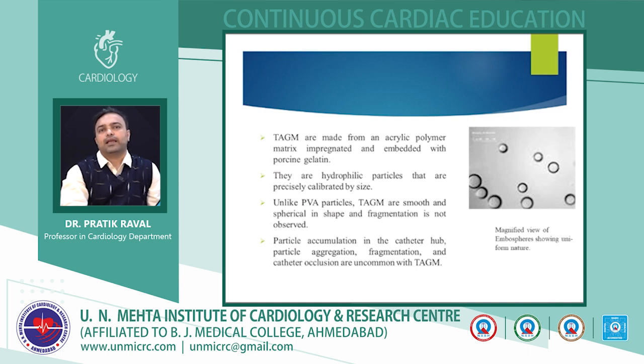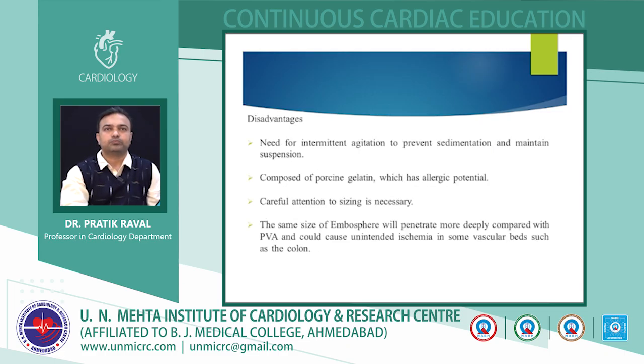Particle accumulation in the catheter hub, particle aggregation, fragmentation, and catheter occlusion, which are commonly seen with PVA particles, are usually uncommon with these TAGM particles because of their uniform shape. The main disadvantage of this particle is that they can easily get sedimented, and therefore there is a constant need to agitate the saline. They are composed of porcine gelatin which can cause allergic reaction in some patients,